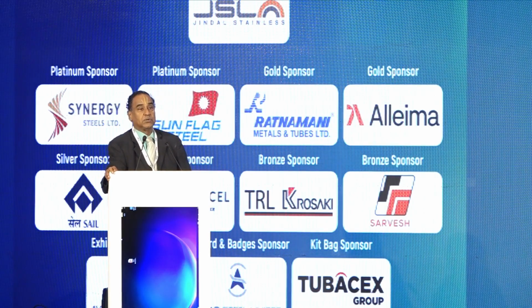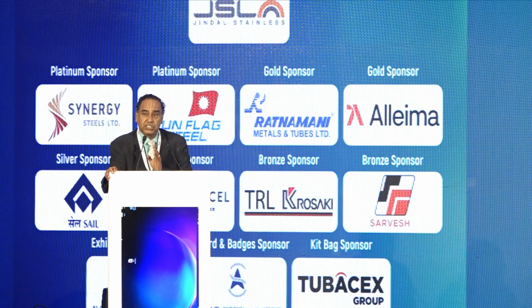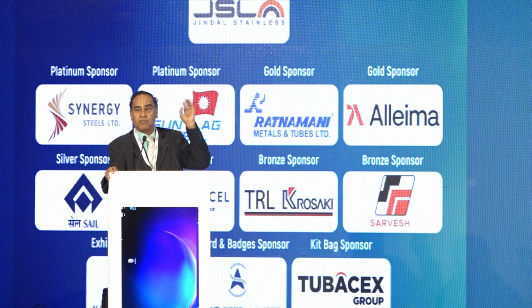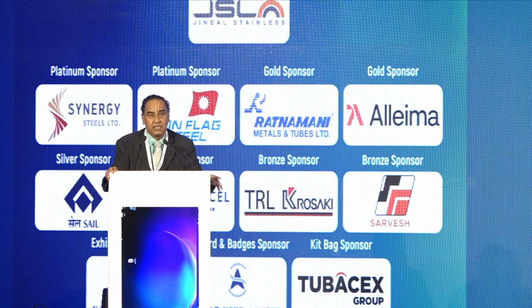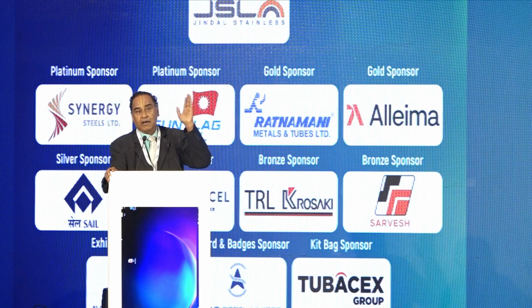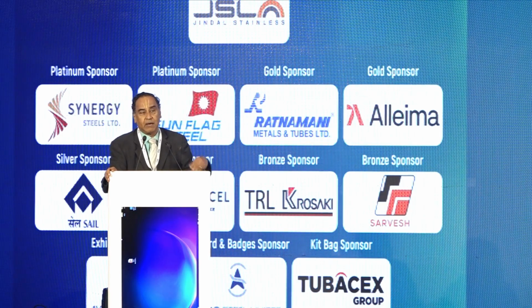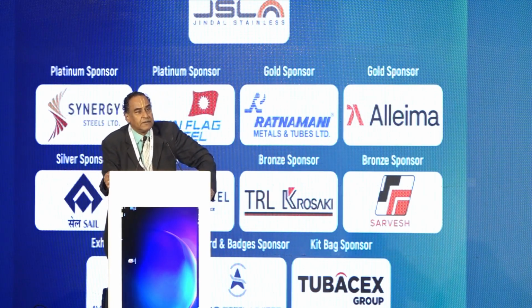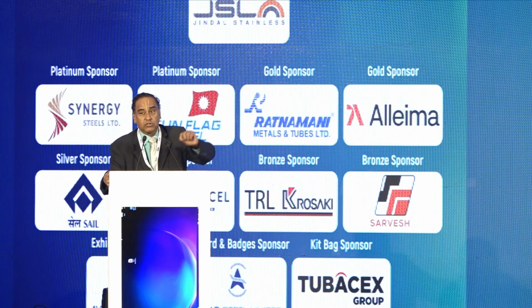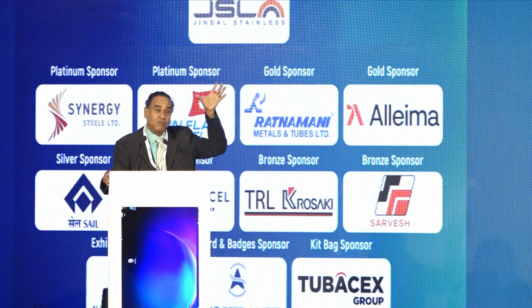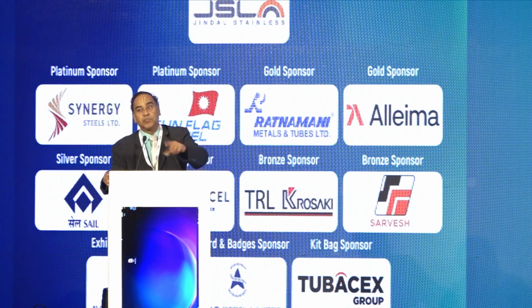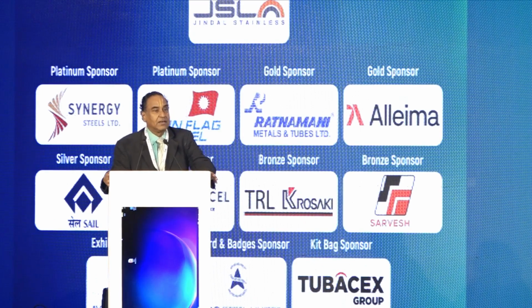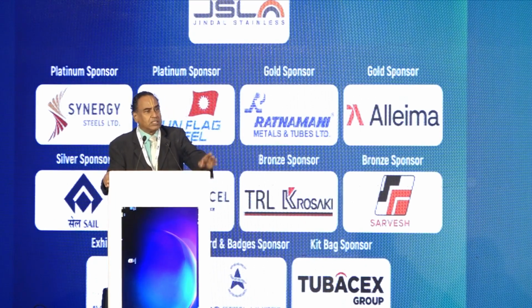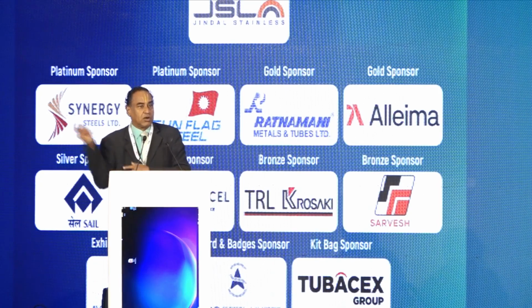And also, there are some conditions in which the plant is being shut down for maintenance. At that time, when it is open, some kind of moisture can enter the place. When the moisture and the corrosion products that are existing combine together, they can produce specific conditions like stress corrosion cracking conditions. Under those conditions, you should avoid those materials that, even though they perform well during the operation, during the shutdown period are prone to suffer the kind of stress corrosion cracking. So all these things will affect the integrity of the plant once you restart it.